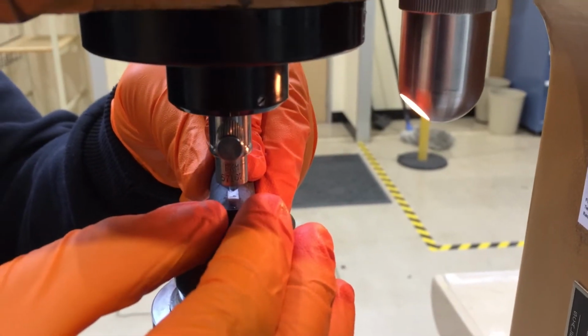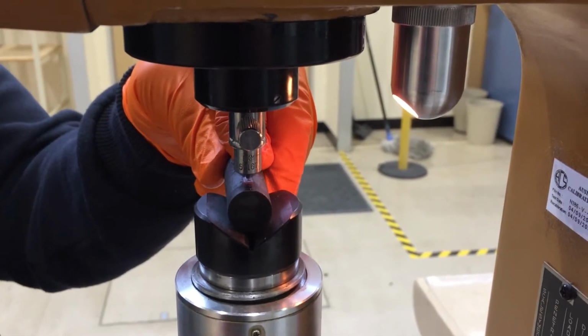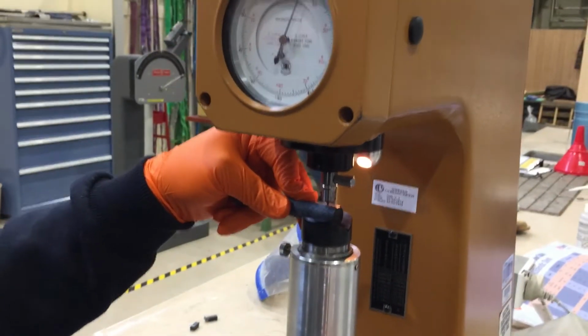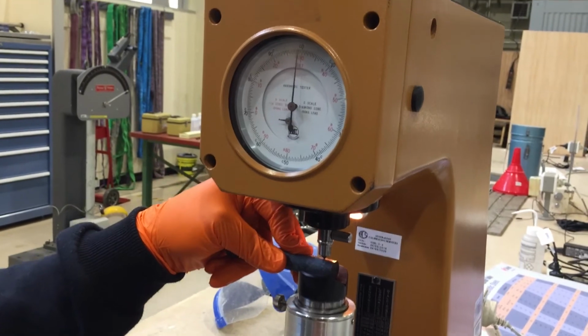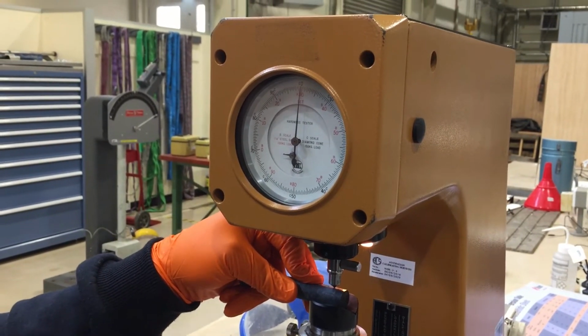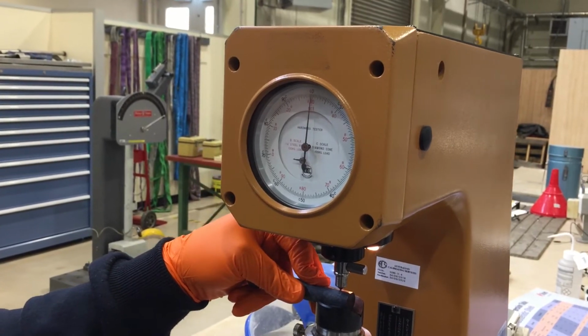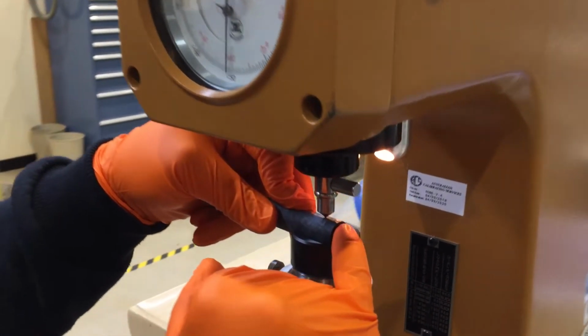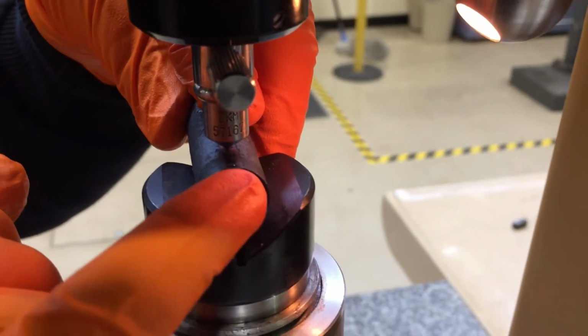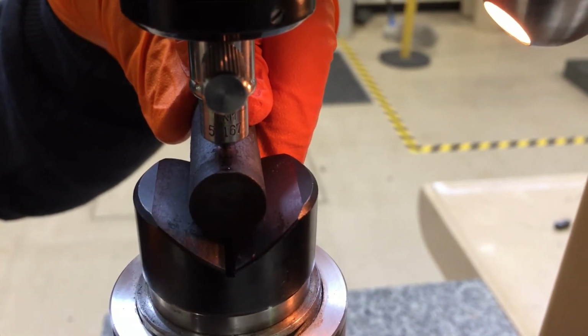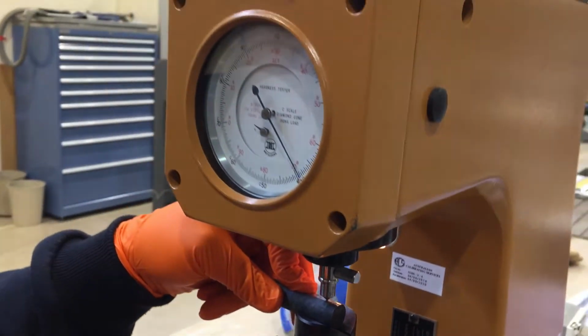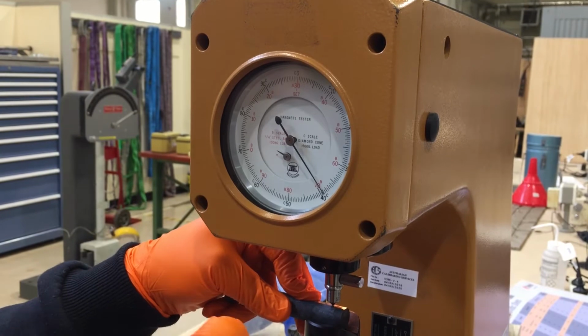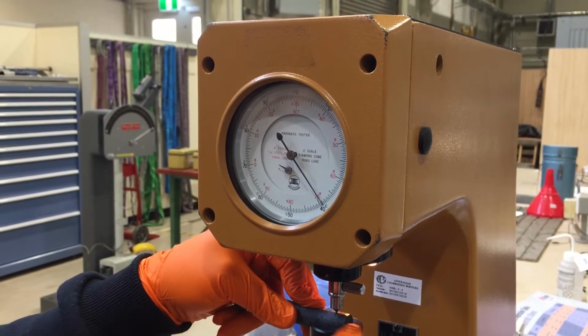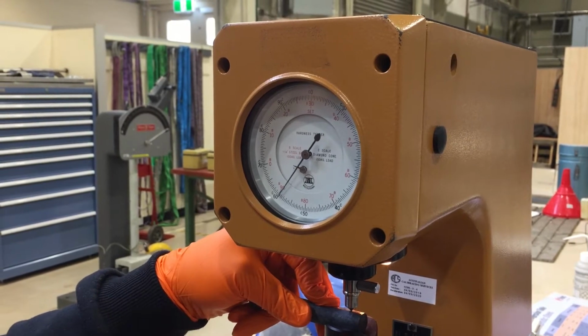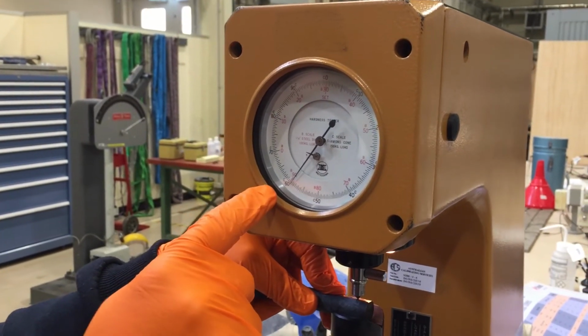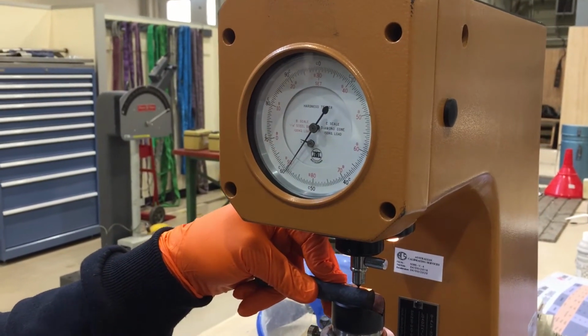Okay, and now we're gonna move to another location. So for example, if we go to location number 4 and then also bring the sample in contact with the indenter and then apply the initial load and define the set point and then start the test. And just if you come here, you can see the indentation at location 1, it's quite visible, that indentation mark there. And we are expecting the indentation mark to be increased as we are moving far from the end, because the hardness is decreasing. And see now, the hardness is lower, so it is about 59 Rockwell C.